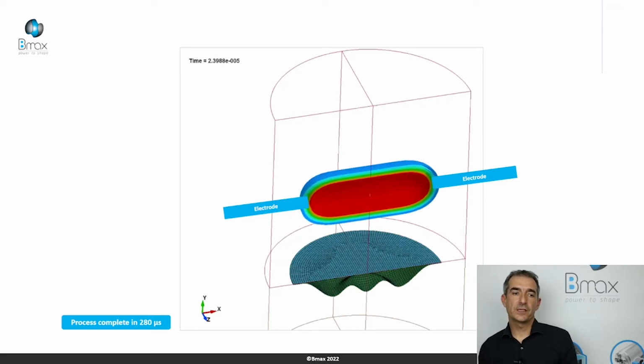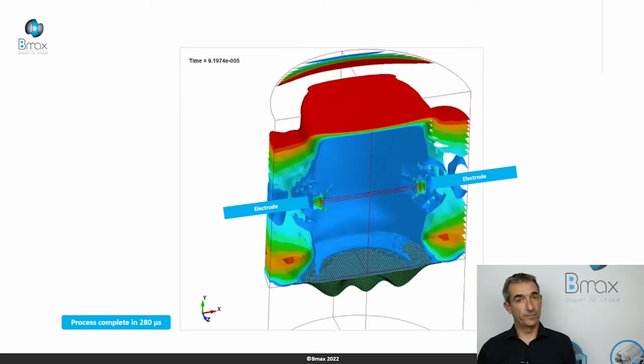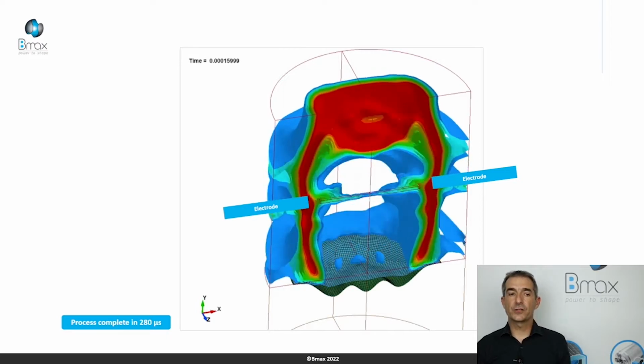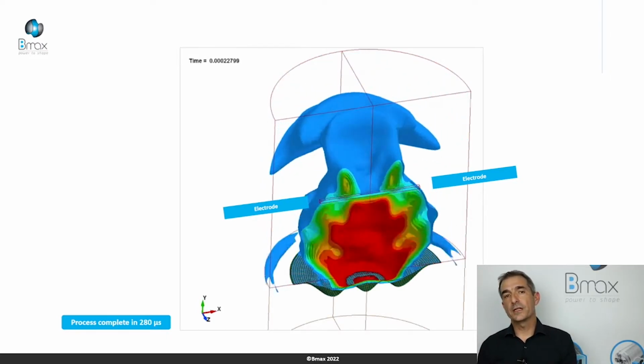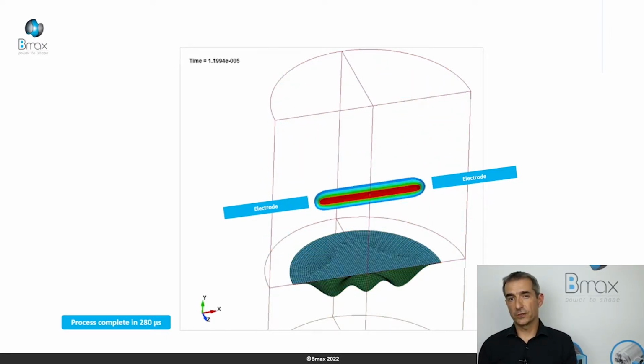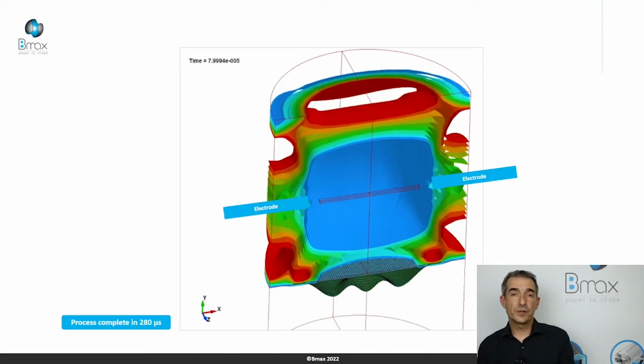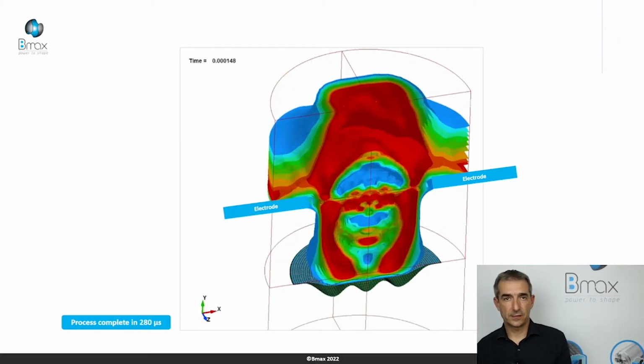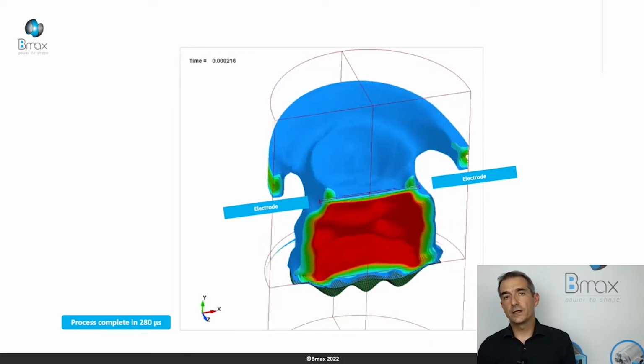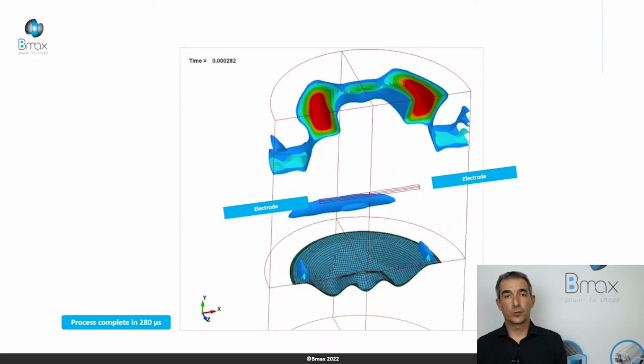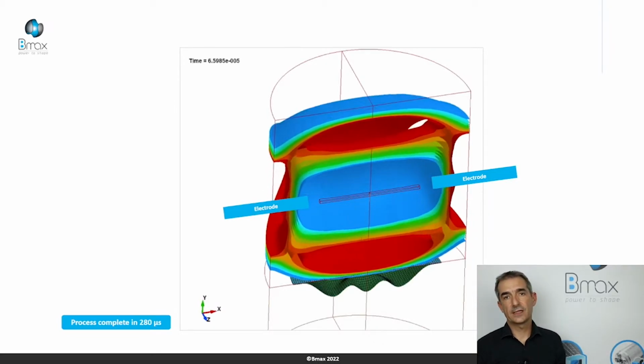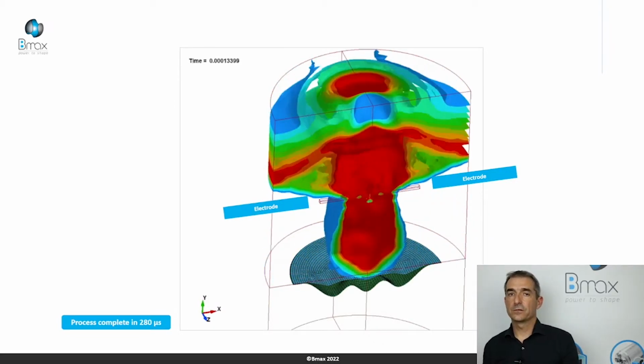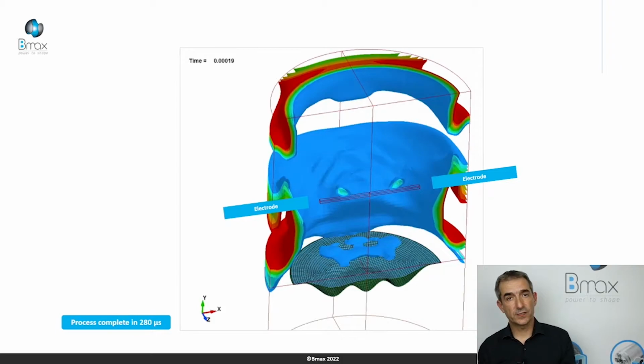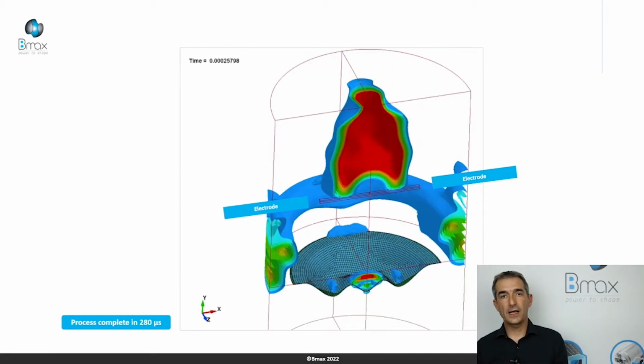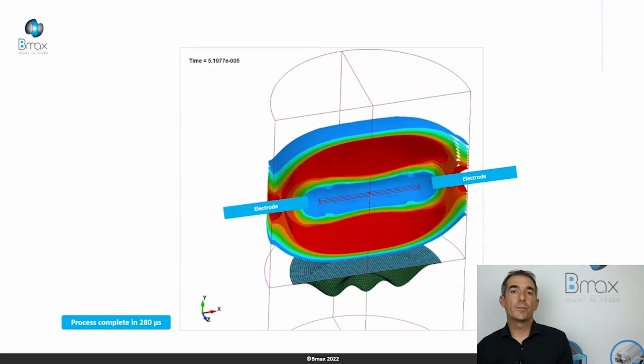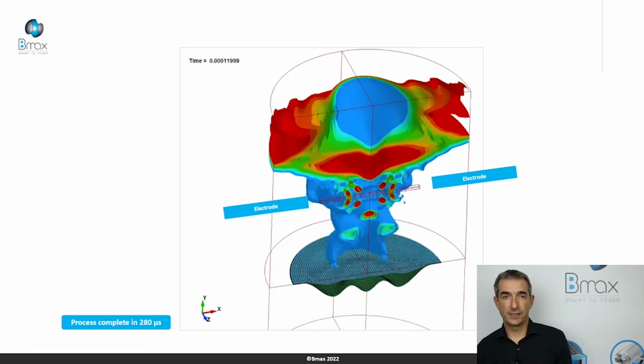As you can see, the first incident wave creates just velocity on the blank. We have a first reflection from the sidewall, and with the combination of the second reflection and the top reflection, we can complete the forming thanks to the combination of the last reflection. All is done in 280 microseconds. So it's one discharge, and we have a 3-step forming. So it's difficult to imagine such a process without simulation. And as you can see, the loading applied on the blank depends on time and space.